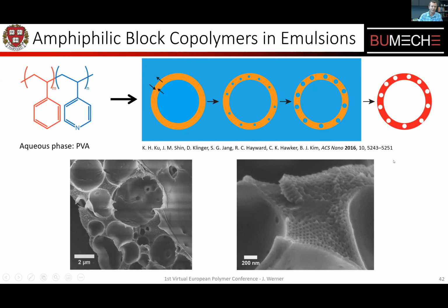And therefore, in our capsule shell, we formed these micron-sized pores together with our nano-sized pores. However, these pores did not cause the capsules to break, very interestingly, even though these ones were not including the cross-linking chemistry, the thiol-ene chemistry I described before. So it's a very interesting way potentially of making hierarchically porous shells for these systems.